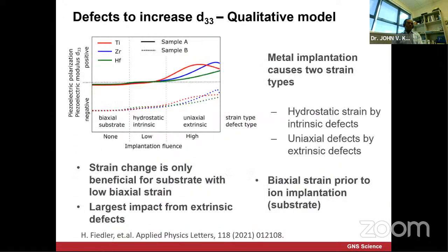So moving on, we also looked at various samples. The reason we are not saying here what is sample A and what is sample B is because of commercial reasons. We have filed a patent, and it has gone through already. So let's assume samples A and B for commercial reasons. And you can see that, depending on the fluence, we are able to change the biaxial, and we use even different biaxial substrates, hydrostatic, intrinsic, extrinsic. We are able to change the piezoelectric polarization from the positive side and the negative side, everything.